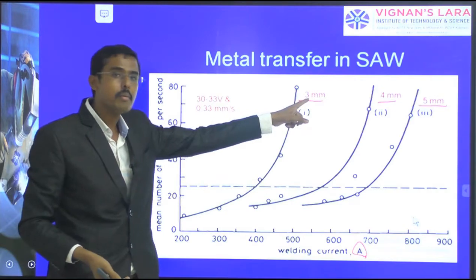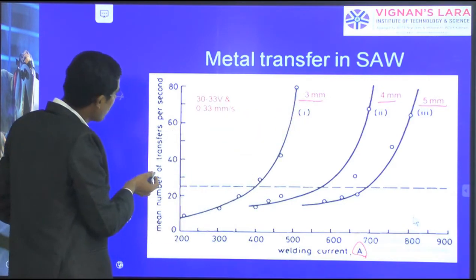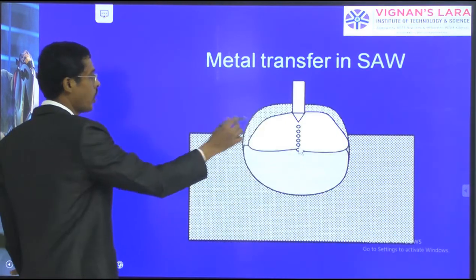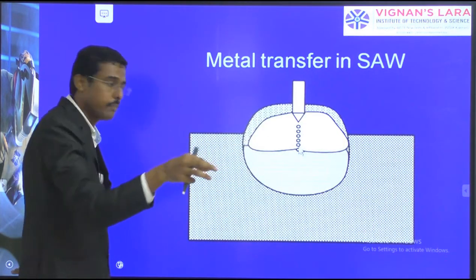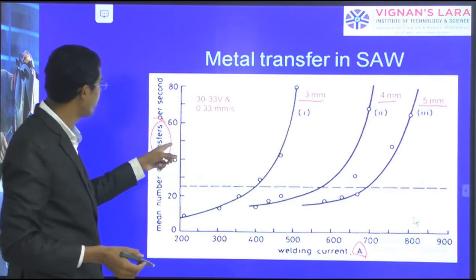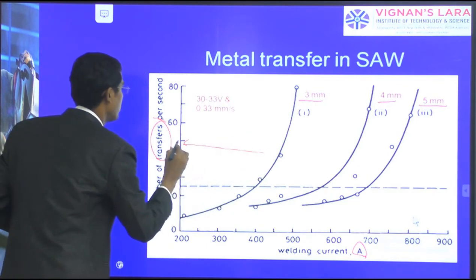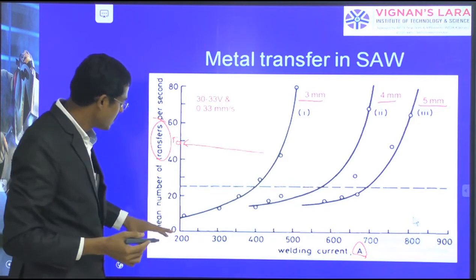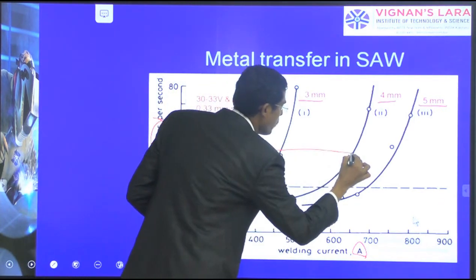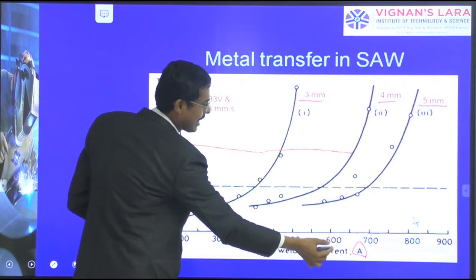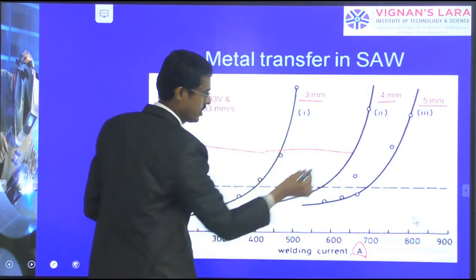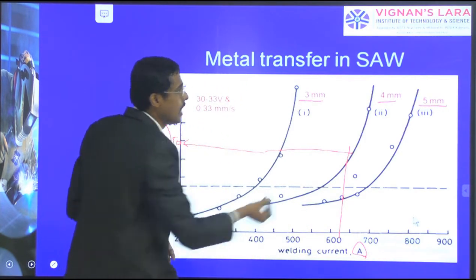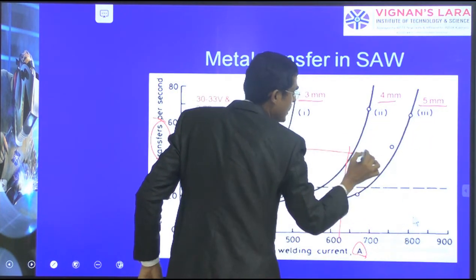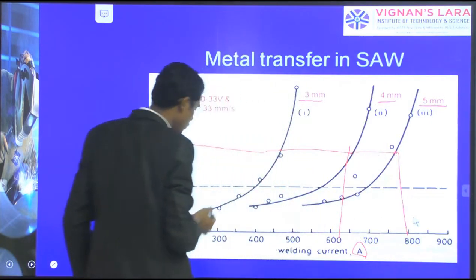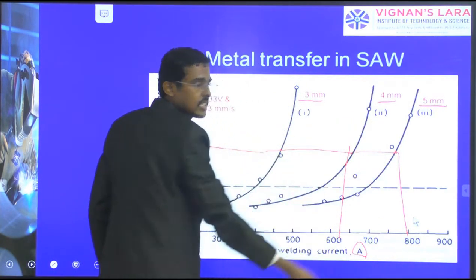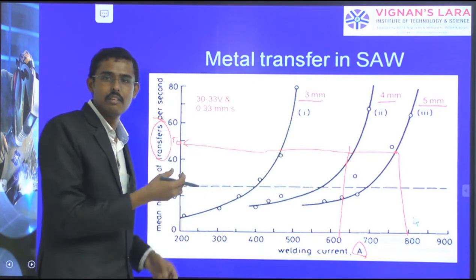See, for the 3 mm electrode, you can see the number of transfers. This means I am talking about these transfers, how many drops are melted and deposited. It is about 50 drops. But similarly, when it is increasing, the same point is reached for the 600 amp current with the 4 mm electrode, it reaches here. In the case of the 5 mm electrode, it reaches this point only at 800 amp. So increasing current, increasing diameter, we have to check this neatly.